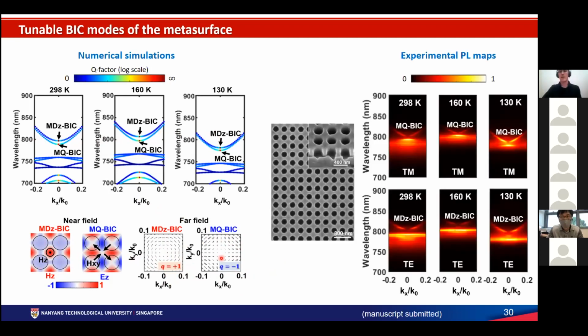The realized structure with nanoimprint lithography is shown here. You can see that it is a very nice flat surface. And indeed, the experimental PL maps show emission in both TE and TM, where you can identify the two BIC modes in emission. You can see there is a clear black point appearing, a vanishing intensity, here.